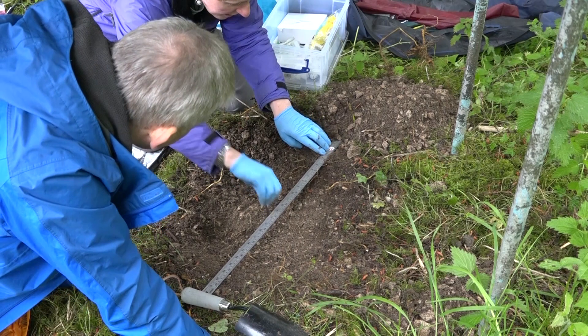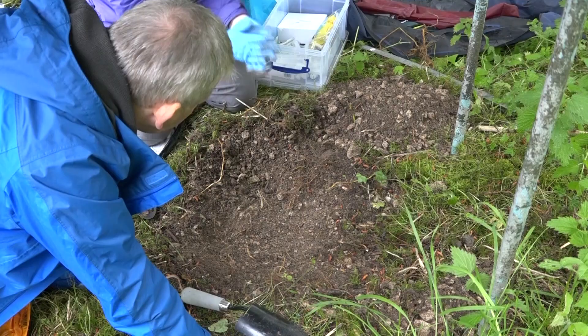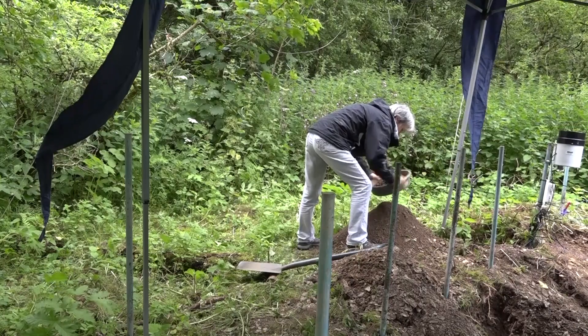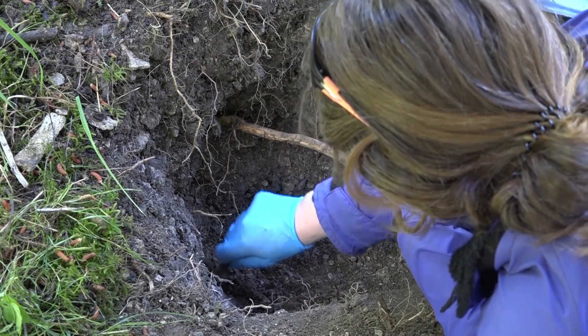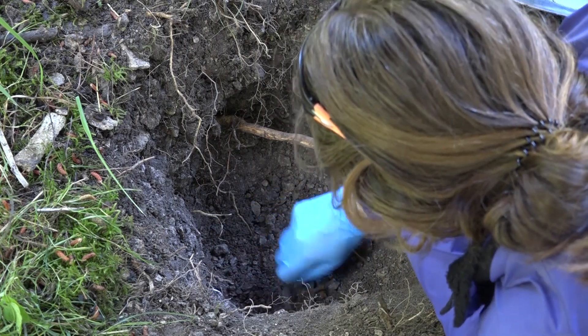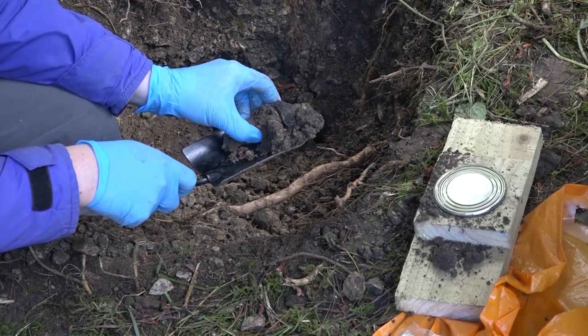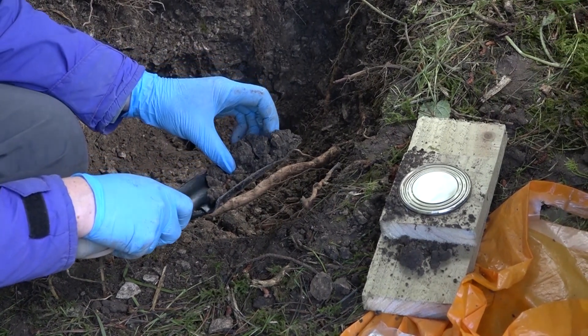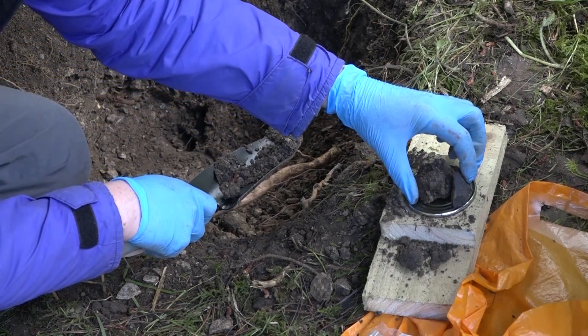We've dug them up a little bit early because of another reason for investigating samples that's come online since then — the interest in glass corrosion brought about by burying our vitrified nuclear waste in a subsurface repository. This new interest meant we got some funding to dig them up at 50 years. Alongside the original archaeological glass samples, there are samples of UK glasses, US nuclear waste glass simulants, and a Russian glass as well.